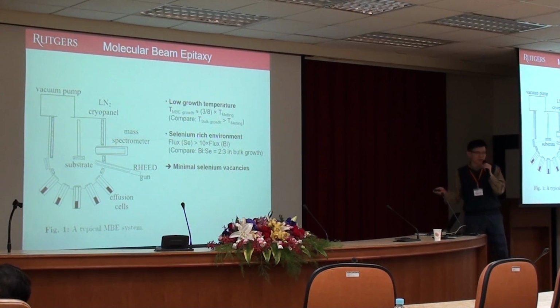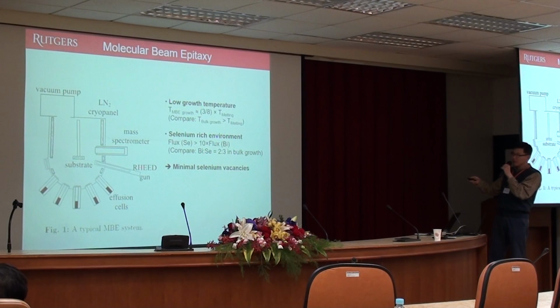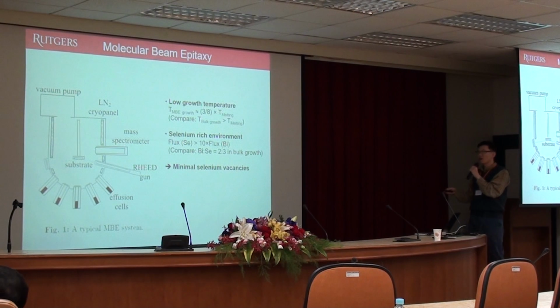Why is this good? Because the defect density is thermodynamically determined. So if it is formed at high temperature, thermodynamically you have to have many defects. If it is grown at low temperature, you have fewer defects. So you can in principle achieve fewer defects by growing at much lower temperature. That's to your advantage. Another thing is, because we know that it is due to selenium vacancies, you can grow this material in highly selenium-rich conditions, 10 times, 20 times, 30 times more selenium. This is beneficial to minimize selenium vacancies. So both help.